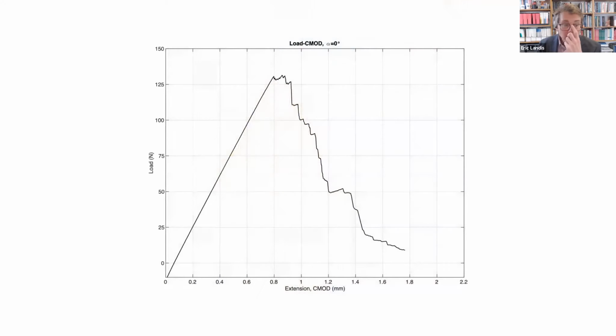So a typical analysis shows a load CMOD curve, very characteristic with the linear pre-peak, and in this case, relatively stable post-peak. While this test is taking place, we're taking digital pictures, and these marks show where we have photographs. From those digital images, we can measure crack length. So as the CMOD grows, so does the crack length.